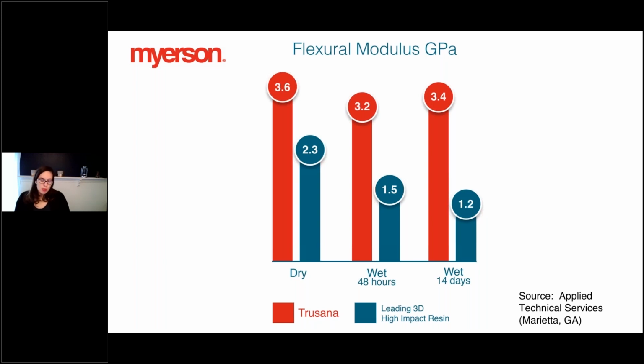What we did as part of our analysis of Trusana is we measured the flexural modulus and compared it to the leading 3D high impact resin. And the results are great. I want to mention too that the results I'm showing you were conducted and verified by an unbiased third party, so these were done out of house. If you test the Trusana material dry, without any water exposure, you get 3.6 gigapascals of flexural modulus. And if you compare that to the leading 3D high impact resin, it significantly outperforms.